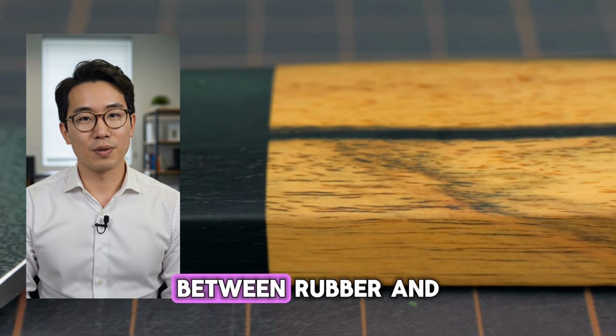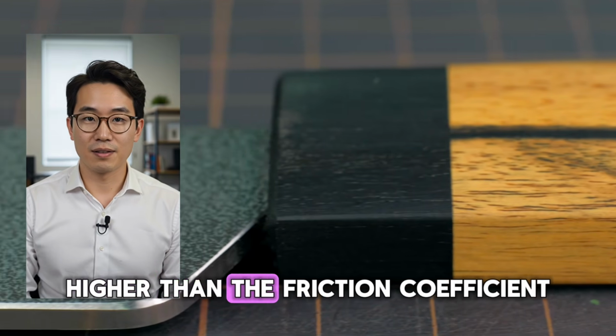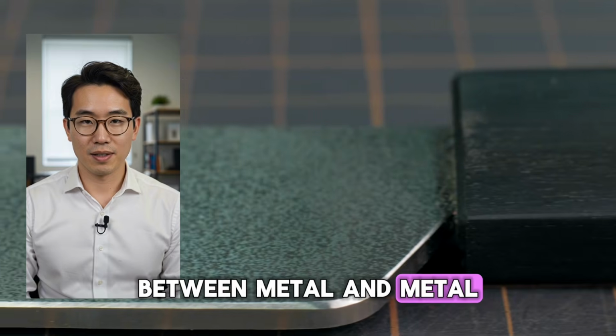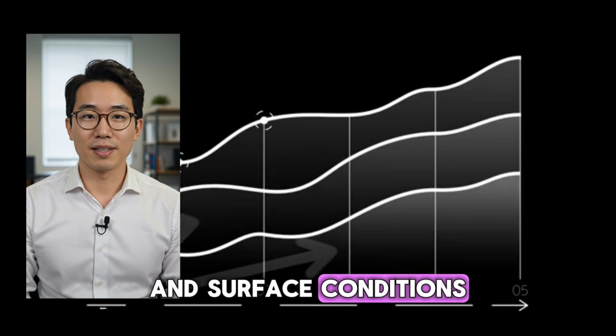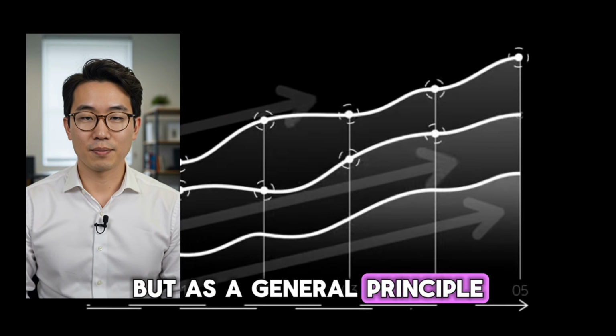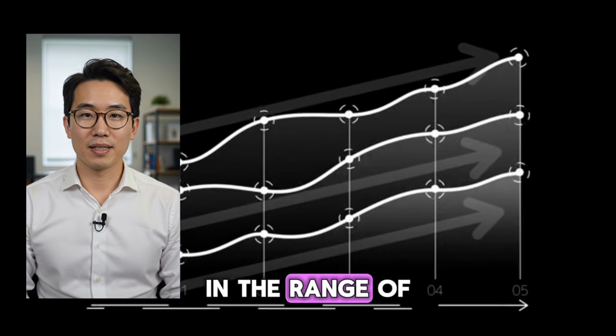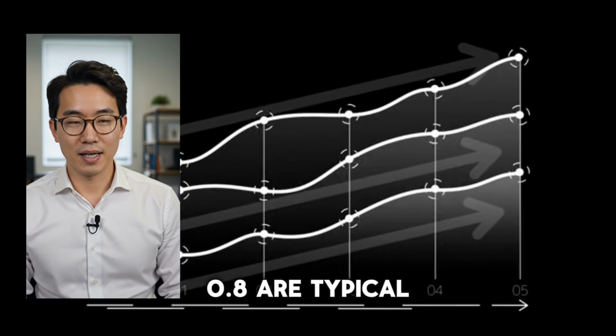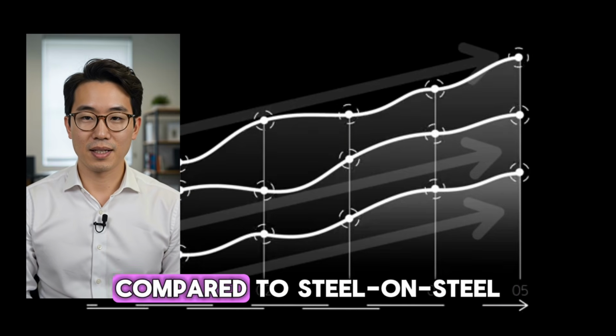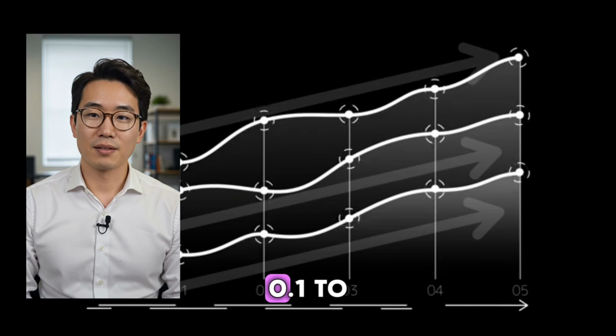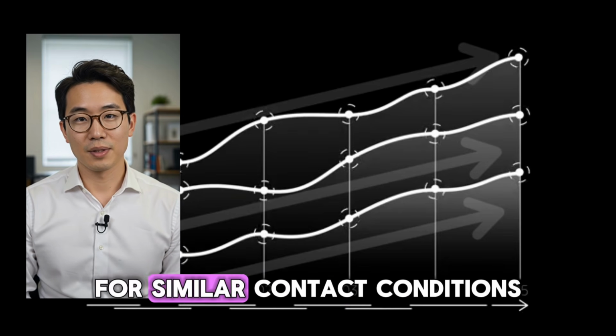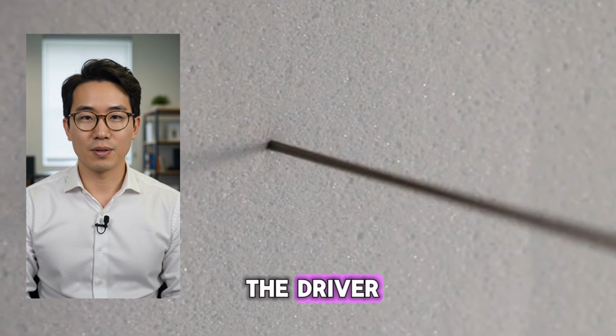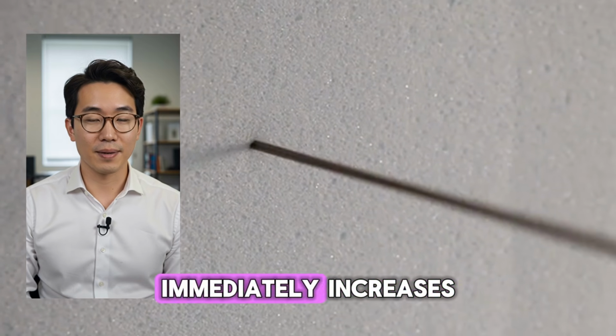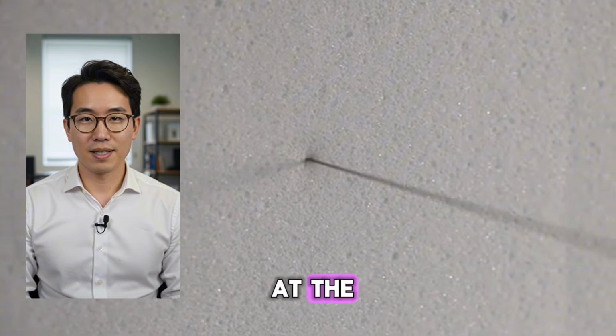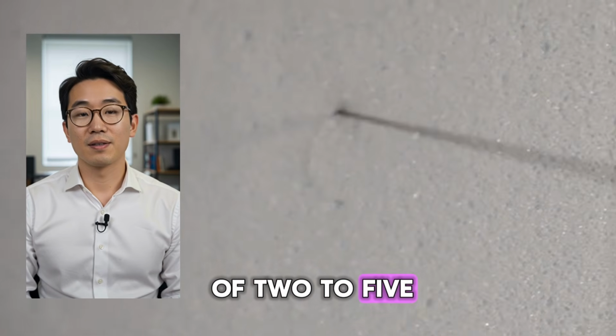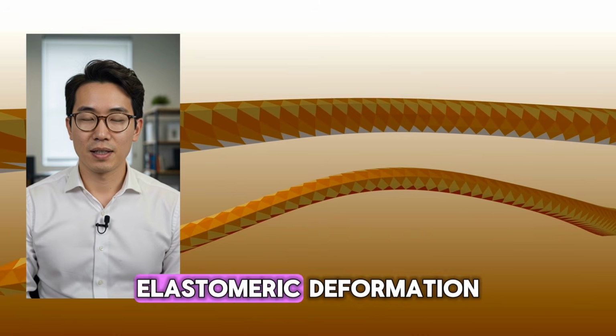The friction coefficient between rubber and metal is significantly higher than the friction coefficient between metal and metal. Values vary with specific materials and surface conditions, but as a general principle, rubber-on-steel friction coefficients in the range of 0.5 to 0.8 are typical under dry contact conditions, compared to steel-on-steel coefficients in the range of 0.1 to 0.3 for similar contact conditions. A rubber layer between the driver tip and the screw recess immediately increases the static friction force at the interface by a factor of 2 to 5. The second mechanism is elastomeric deformation.